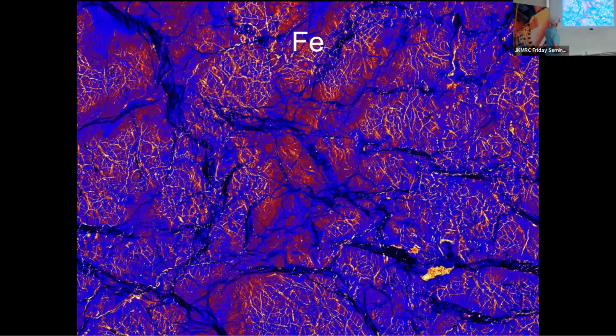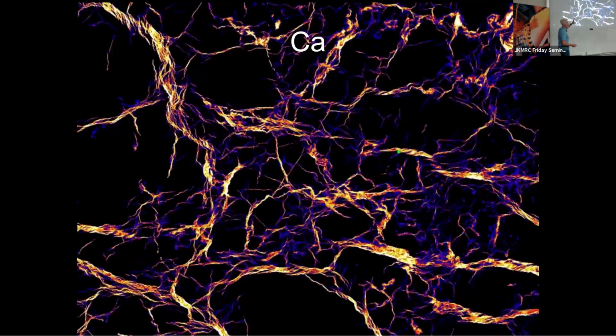For the larger fractures that are here, that's where we get our calcium signal. So we shift into that. And it looks kind of like Loki's timeline with the spirals and everything that's there. But this is our mineral carbonation process that's going on. That's breaking open the peridotite. And when we went looking for DNA within the sample, we found it only in the carbonate. Okay, so we've got biosphere that's going on here, and promoting mineral carbonation within this system.